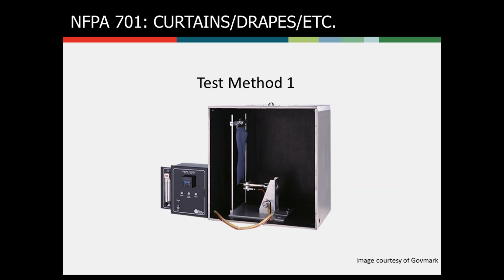And so the test has two ways that you could fail. If any fragments or drips fall off the specimen and continue to burn for more than 2 seconds, then that's a failure. And additionally, afterwards, you weigh the sample and you determine if the weight loss was greater than 40%, then that's also a fail. So in this case, you would check the mass of the specimen before the test, check it afterwards. If more than 40% of the weight has been consumed, then you've failed.